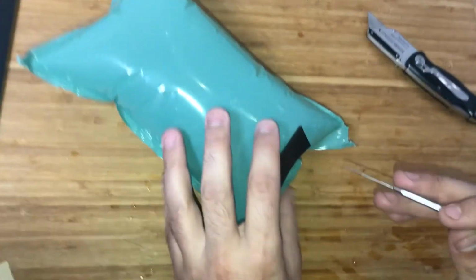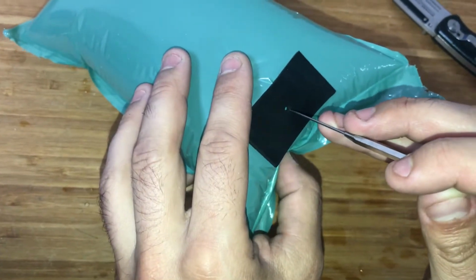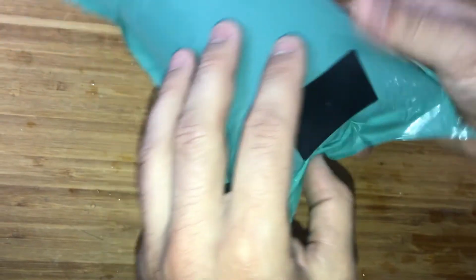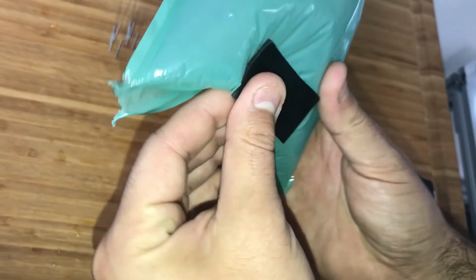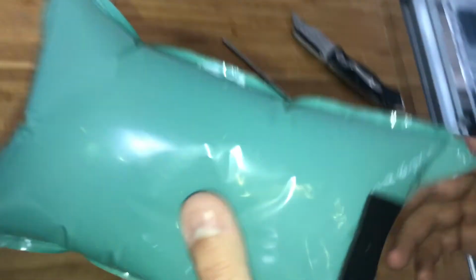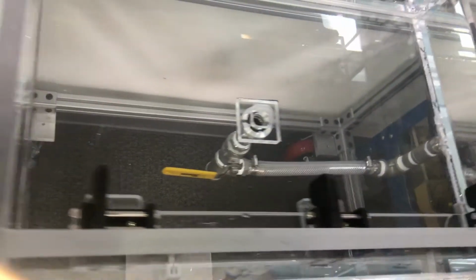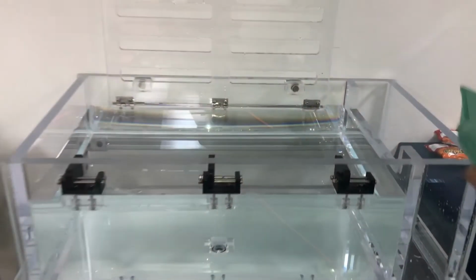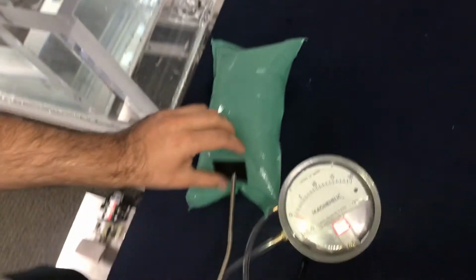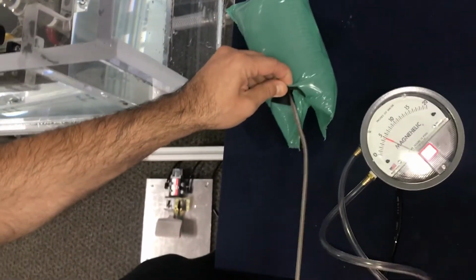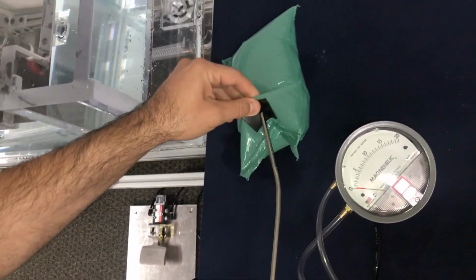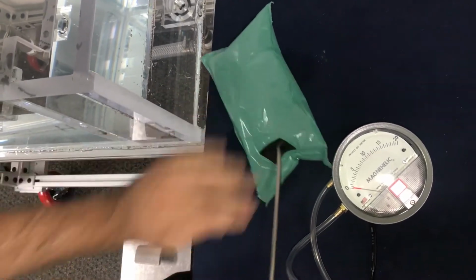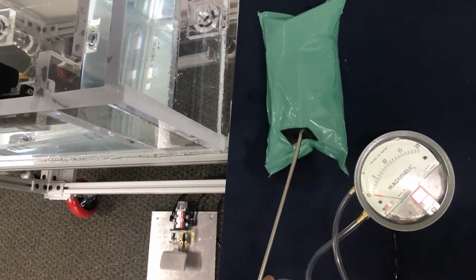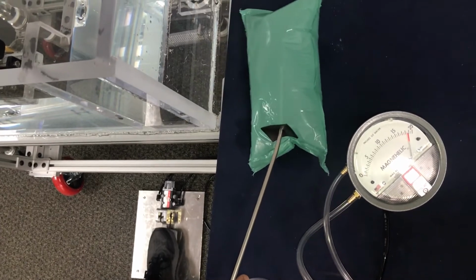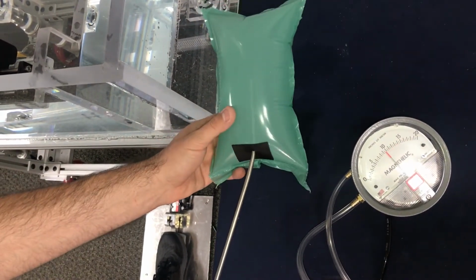And then we will go ahead and puncture a hole through here, and we'll make sure that we puncture it through the punched hole. Now the reason we have the septum tape is because we will insert the probe now, and the septum tape creates a good seal between the pouch and the probe. And now the probe is in, and then with your foot, as you can see on that pedal, press the pedal and let your test specimen be inflated with air.